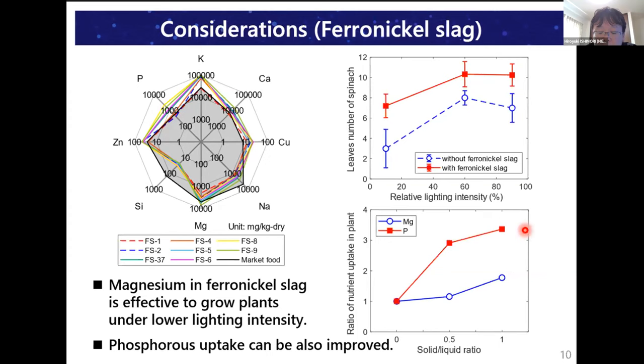The right shows the efficiency of ferronickel slag. The top one shows a superior growth using ferronickel slag, like the red line, than not using ferronickel slag, like the blue one. Additionally, as shown in the bottom one, ferronickel slag provides some magnesium for photosynthesis, resulting in enhancement of phosphorus uptake, like the red line.